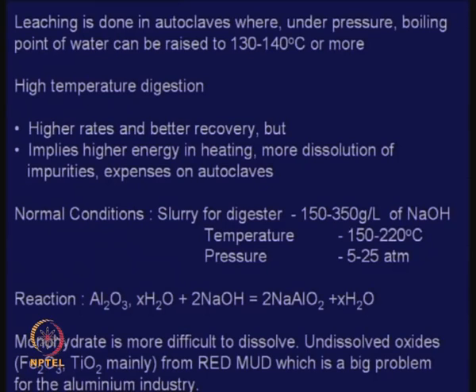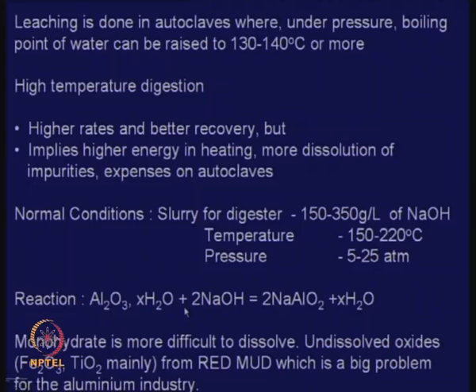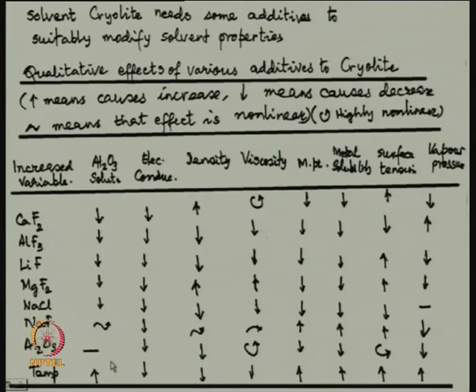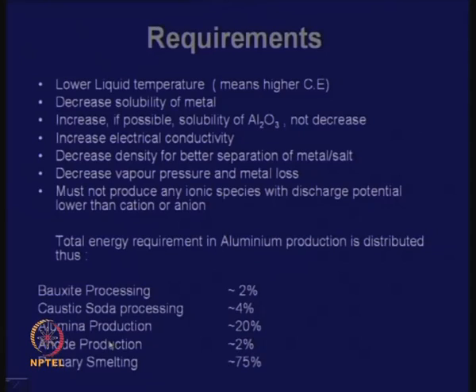So, there are some contradictions: higher temperature digestion means higher rates and better recovery, but higher energy in heating, more dissolution of impurities also, and expenses in autoclaves. Normal conditions will be 150 to 350 gram per liter of NaOH, temperature 150 to 220 degrees, pressure 5 to 25 atmospheres. The reaction is alumina with NaOH giving sodium aluminate. Monohydrate is more difficult to dissolve. Undissolved oxides, Fe2O3 and TiO2 mainly, form the red mud, which is a big problem for the aluminum industry.